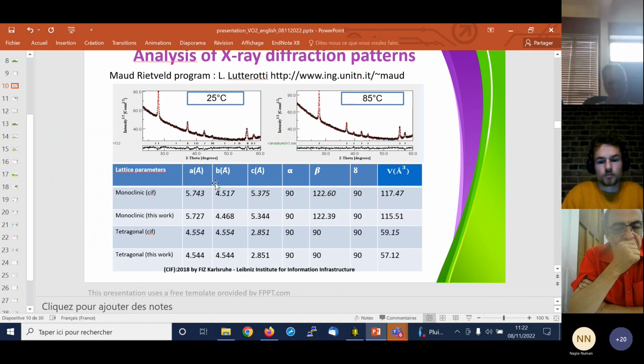So you can measure very accurately the content of the doped films. And in this case, for instance, for the 3%, they measured 2.7%, okay, slightly less. But we have exactly the right values. They were controlling very well the amount of doping, and in a quantitative way, while in many cases, some people say, well, I dope, I have 3%, but they don't know exactly how much the right content of the percentage is.